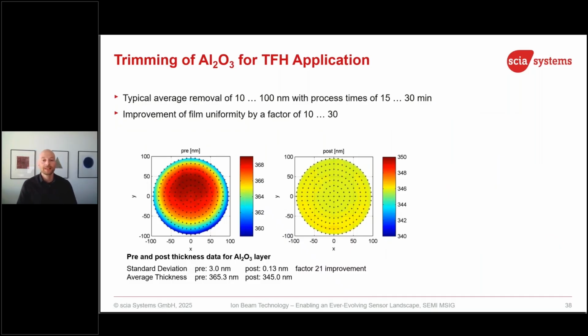Here we have a real example from production. We have a 200 millimeter wafer, with some alumina on top. So that's the surrounding matrix I mentioned already. It has a certain thickness variation of about 1%, so not too bad, but not good enough for our customers. They need much better. And we applied ion beam trimming and reduced the standard deviation here from 3 nanometers to 0.1 nanometer, a factor of 20 improvement. Such a process on that 200 millimeter wafer with alumina, alumina etches rather slowly, takes 15 to 20 minutes. We have a lot of other customers where wafers need only 5 minutes to get this very good uniformity.